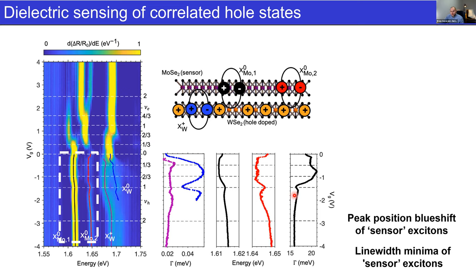And this is of the bright black exciton here. And this is what one would expect as you go towards an ordered state. And also we expect a blue shift in energy as we have a more insulating type sample that's in contact with a dielectric environment. So this is fairly consistent and agrees again with our assignment of these peaks. As well, if we look at, for instance, the line widths of these two peaks that are in the WSe2 intralayer excitons, we see a line width collapse as we get towards an ordered state of the Mott insulator again.